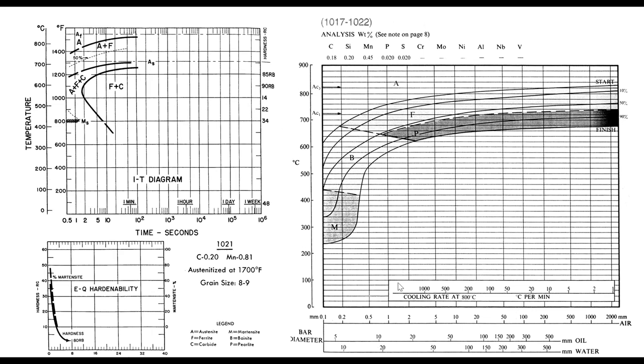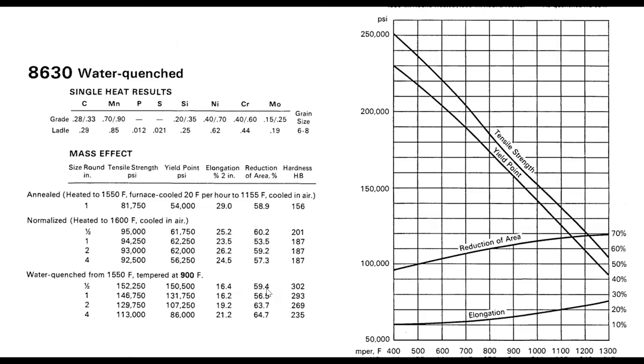That's what these diagrams are. These are heat treatment diagrams. This says that for a one inch bar in water quenching, I still get this ferrite. I don't get the martensite that I want. In fact, I really can't make it thin enough and quench it fast enough. This is a Jominy curve where I quench the end of a one inch bar and only on the surface of the one inch bar do I get martensite. Other than that, the hardness drops rapidly. So if I really want better properties, I have to add alloy content.